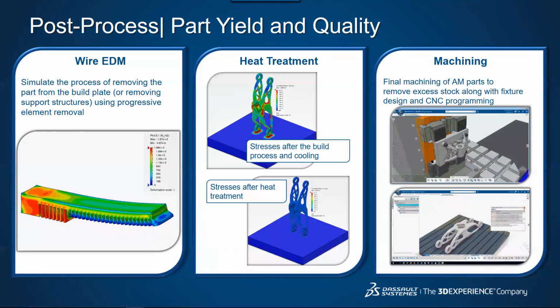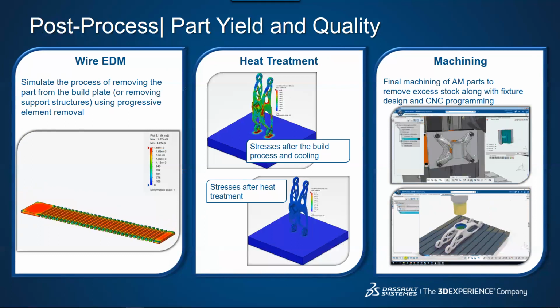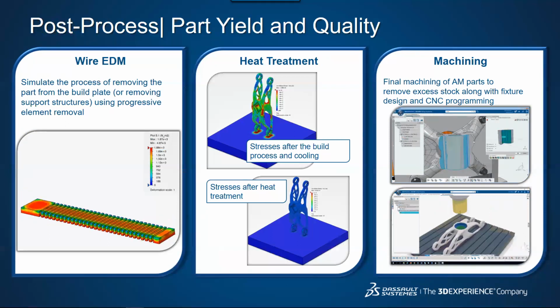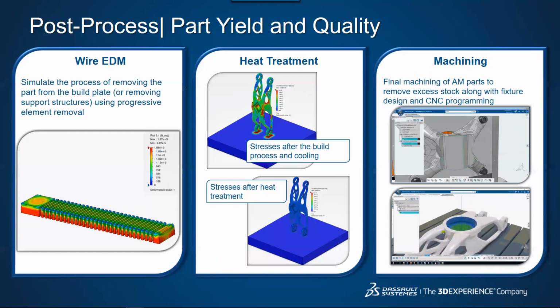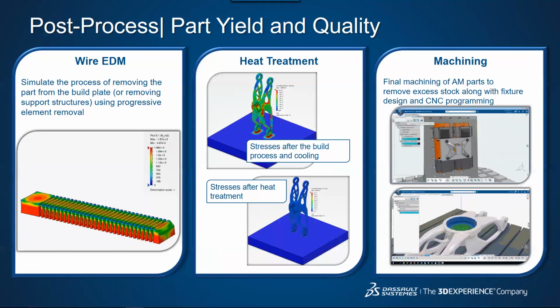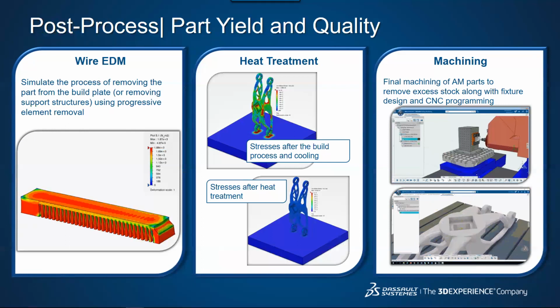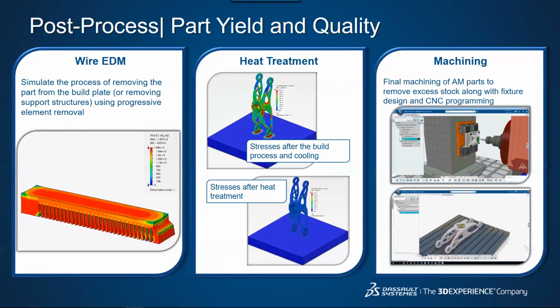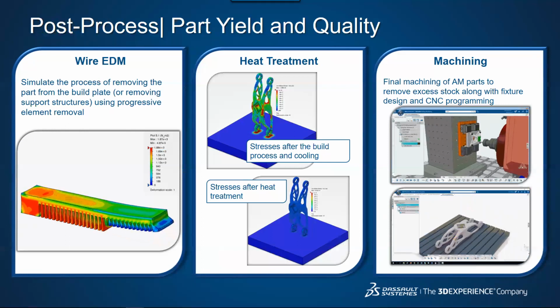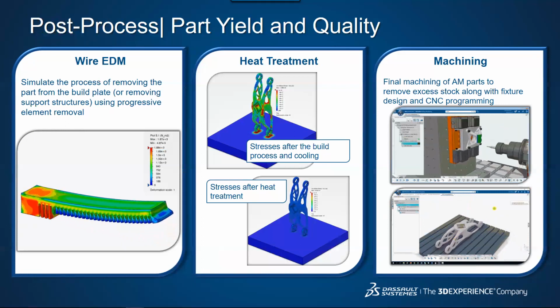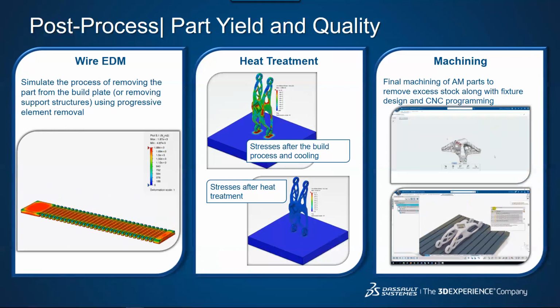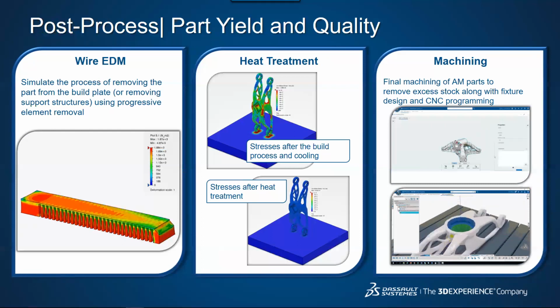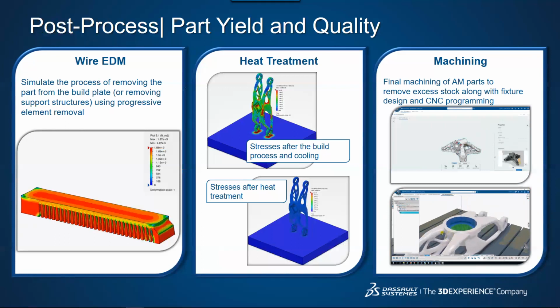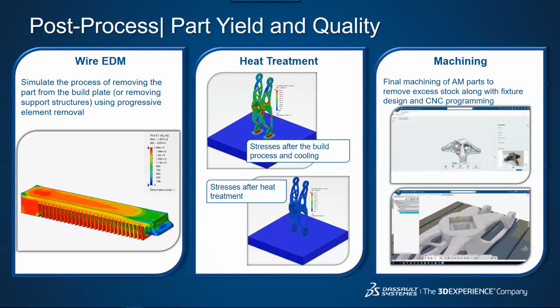So we can use progressive element removal to simulate wire EDM. And then we can also apply heat treatment thermal cycling to simulate that reduction of build stresses. And then we can include the distortions of the final build part in our NC machining code, and this can help you with fixture design and your NC machining programming.